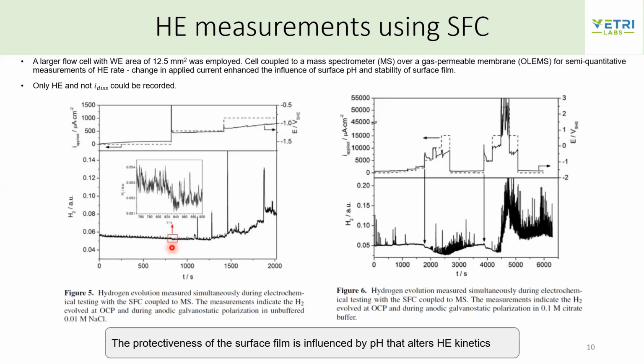They tried to compare the unbuffered solution with the buffered solution. What they found is that in unbuffered solution, the pH at the metal surface was changing drastically, so they were able to see that the fluctuation was really high, and the hydrogen evolution current constantly increased.